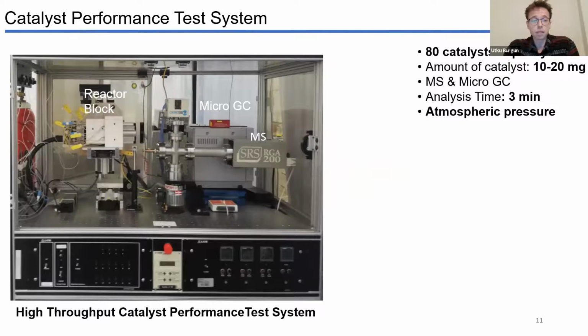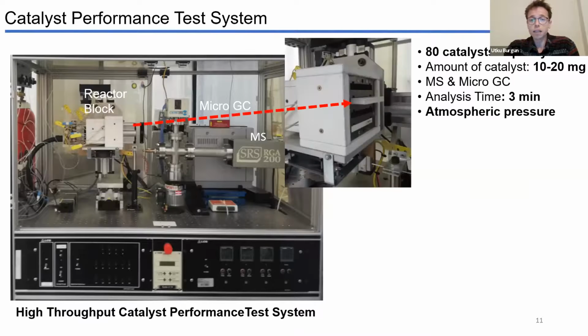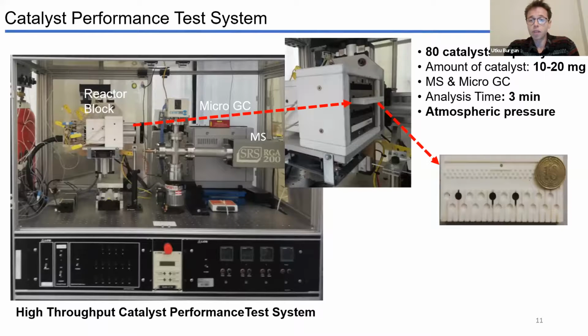At first, the performance scanning test of those catalysts was performed by using a high-throughput catalyst performance test system. In the test system, there is a heated reactor block, and there are 4 reactor plates, each having 20 microreactors with a diameter of 4 millimeters. So the total capacity of that system is 80 catalysts. And due to its micro design, it requires only a small amount of catalyst, about 10 to 20 milligrams.